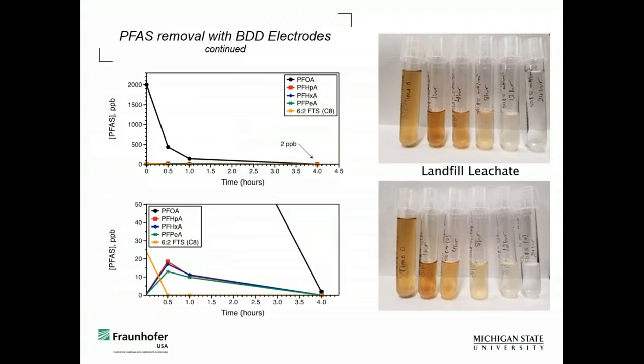But nonetheless, we went a little bit further, and we did the EPA 537 method. And that's what this data shows here. We started with 2 ppm of PFOA. This was more of a regenerate-style solution, so that was a little bit more concentrated. And within 4 hours, we've taken it from 2 ppm down to 2 ppb.